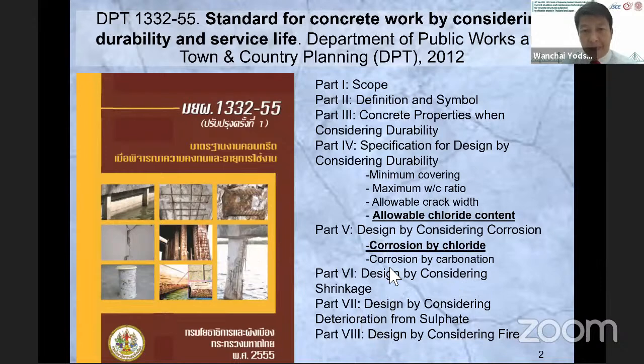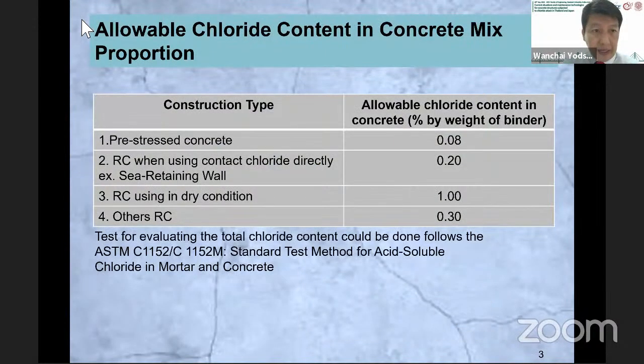For the chloride part, part 4 is the specification for design considering durability. Within this part, we have the specification for minimum covering, maximum water cement ratio, allowable crack width, and also allowable chloride content. And in part 5, we also talk about chloride; it's about design considering corrosion. In this part, we have two types of corrosion: corrosion by chloride and corrosion by carbonation. Next, I would like to explain in detail.